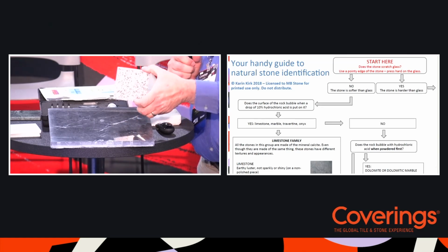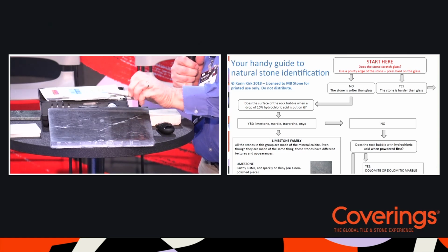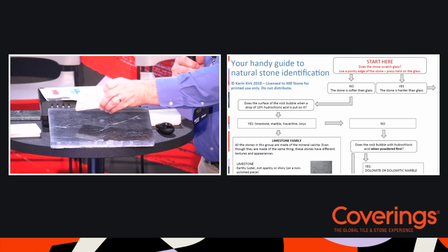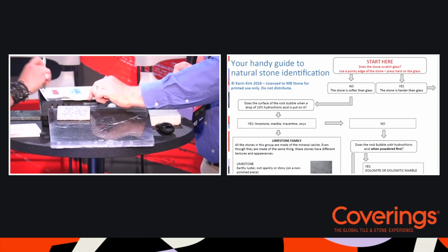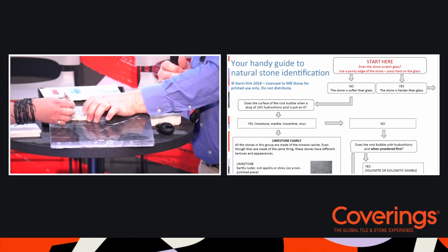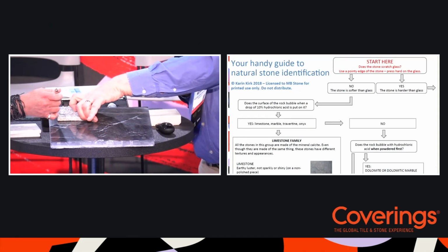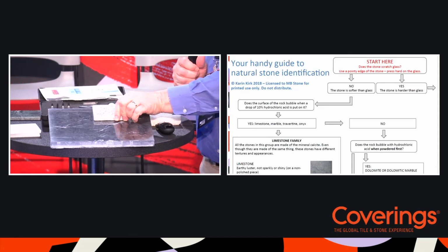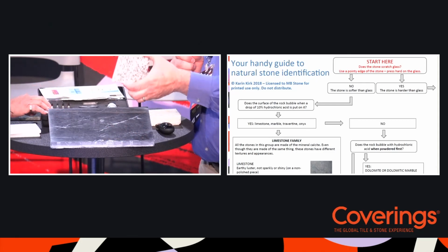But I mentioned a lot of white materials are going to be that calcium carbonate. This, for example, will not. This one I know we've tested a few times. There is no visible etching. I don't know if we've even scratched that one, but just to see where that would be on the scale, let's start here. That catches some. Nope, not yet. That one does. That one does. Yeah, it created a little mark. Again, the white doesn't show up there for you in the audience, but that did a 7. So we're between 6 and 7, and it doesn't acid etch, because I know we've abused this one before.